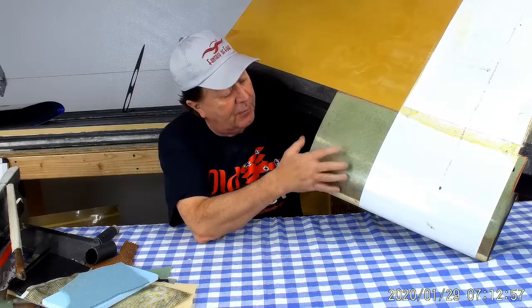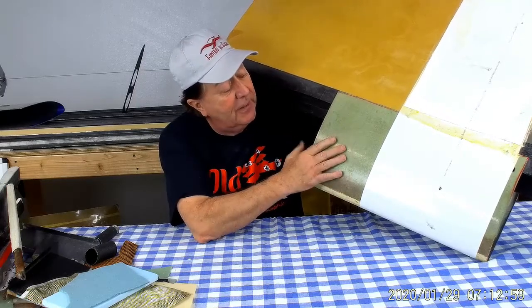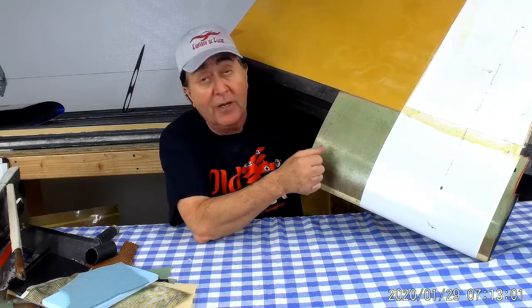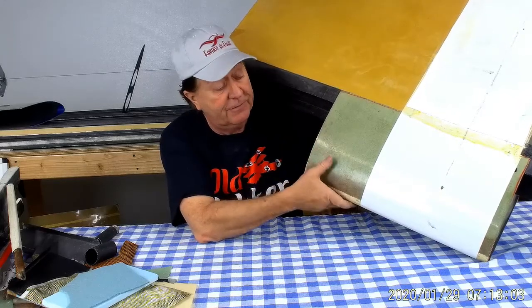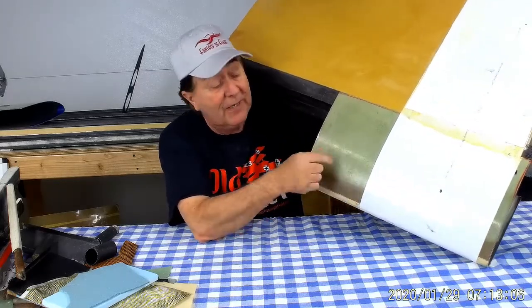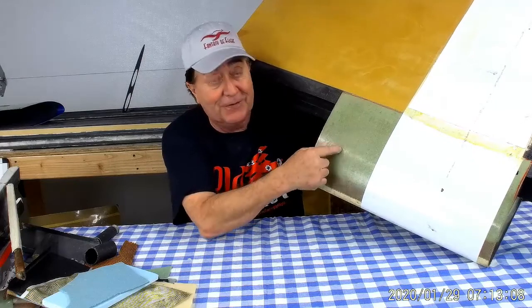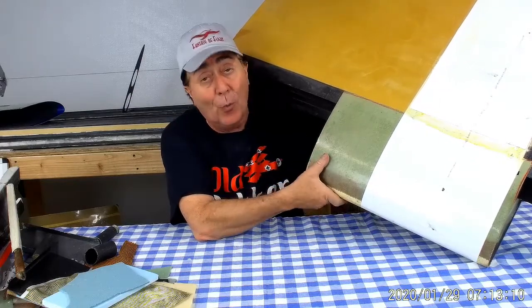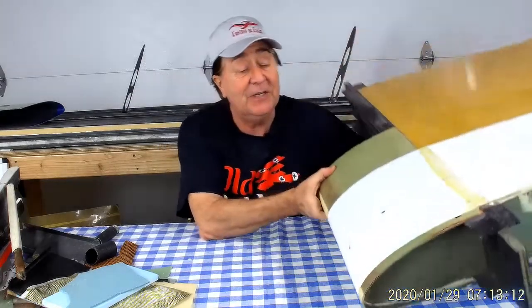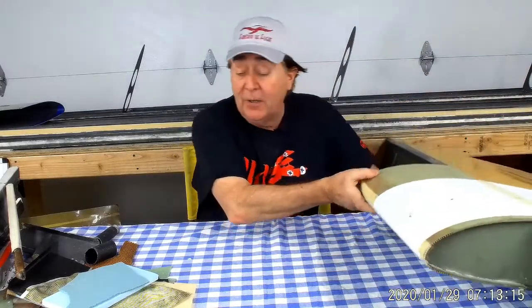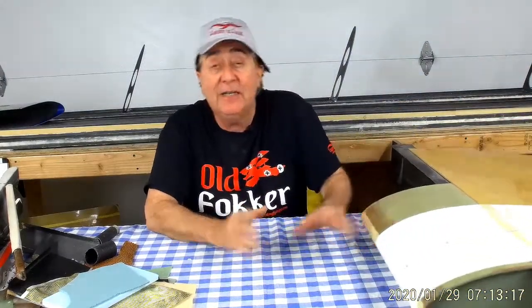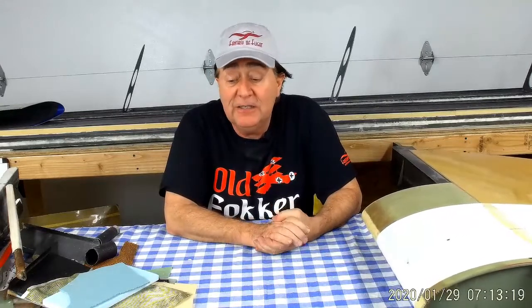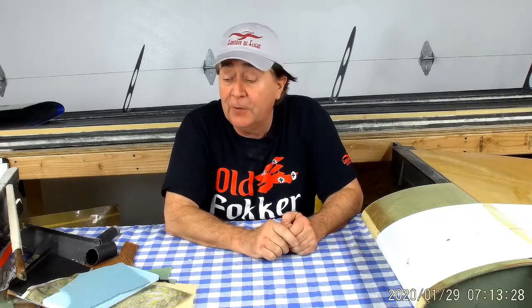Now, this is a practice layup, so it didn't matter, but nominally you would have to throw this part away because it is not bonded securely to the foam. And then when you make the next one, you don't make that same mistake. You transfer this fabric when it's a little more wet and make sure that you get a good bond that way to the foam. But once you have a little bit of practice of using that technique, and you can see it in my videos, it's shown in several of them, you can actually make really good parts that way that are really high strength to weight ratio, and avoid that issue of filling up the foam with extra resin.